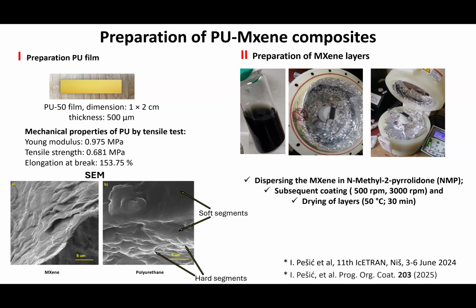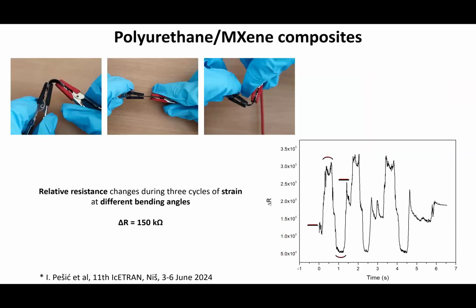And then we get something again. So the polyurethane that we get has very good mechanical properties, high Young's modulus, high tensile strength, etc. And then you put on top of that MXene that is conductive. So we again perform such bending tests. These are bending sensors that we make, and you can see that as you bend the MXene, the sheet resistance that you measure changes. So it's a type of a strain sensor.